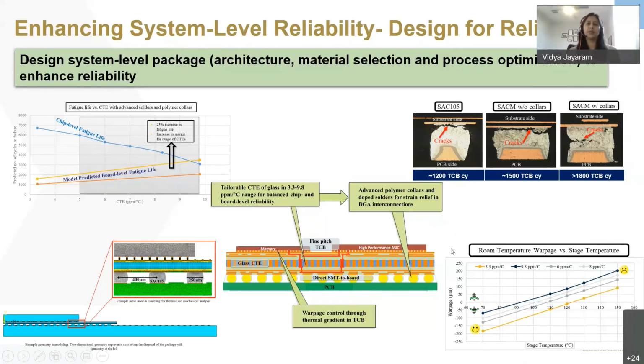And lastly, we used our process condition understanding to minimize the warpage. So we modeled for warpage for different glass CTEs, and we saw interesting results from the model where the direction of warpage changes from negative to positive, or a smile shape to a frown shape warpage with different temperature conditions. And the fact that it went from negative to positive meant that there is a point of net zero warpage that can be achieved by tweaking the temperatures.